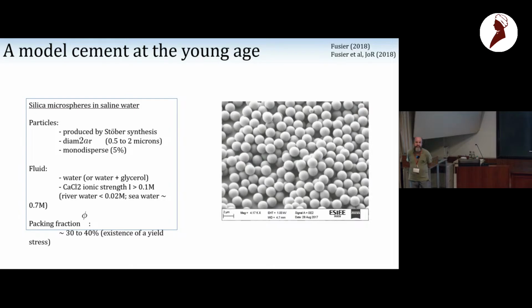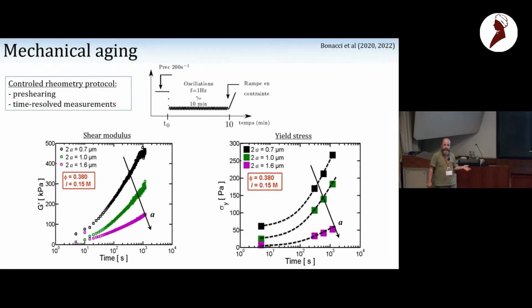And what is amazing is that at 30, 40%, you have a yield stress. And it might be surprising because you're much below the random close packing, but you still have developed a yield stress. So that's typically the kind of data we can get.